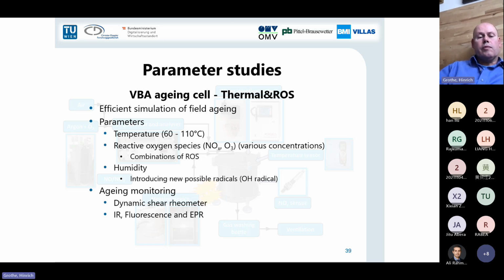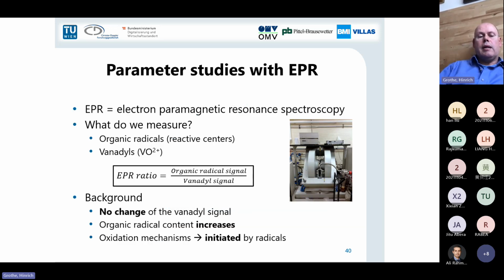So this is a so-called VBA aging cell. We can do thermal aging, but we can also apply these reactive oxygen species. And this is the new point in it, because other aging tests on the market do not have these chemical changes available. So we see efficient simulation of field aging. We can change the parameters, as I already said, temperature, ROS, humidity, and we monitor mechanically and with spectroscopy and see the changes.